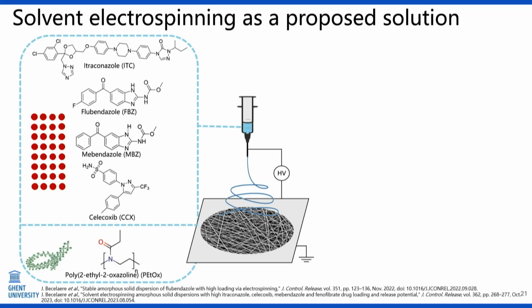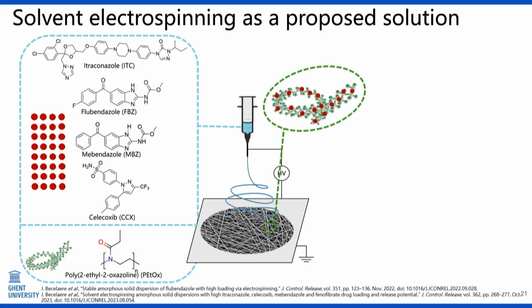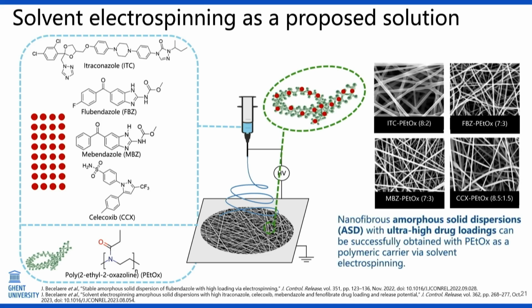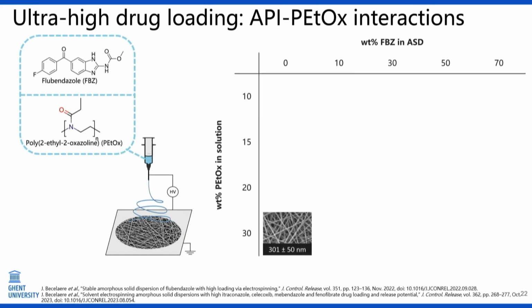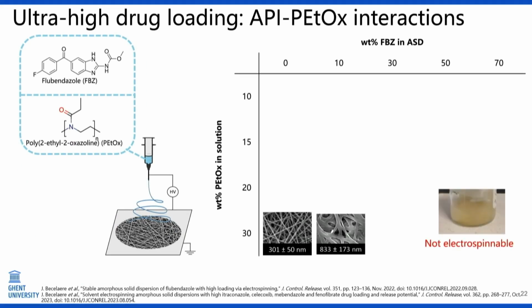So the first question is, can we spin them? And can we spin them to high drug loadings and form this amorphous solid dispersion? Well, I can already say here, yes, we can, to very high drug loadings. And how do we do it? Well, we started off with the normal process conditions for PEtOx only. Then we tried to add the drug, but we could only add very small amounts, 10%. So we were not doing better than traditional techniques, so that didn't bring us anywhere.